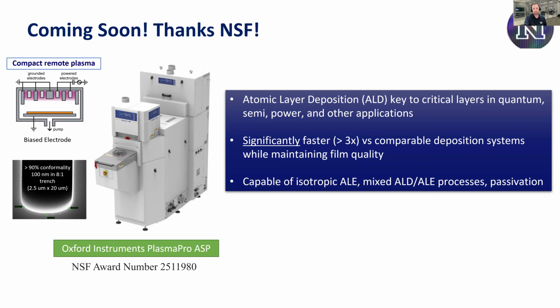We want to be able to control that barrier, but it's really tough because with ALD, when you grow things, if you want like a 2 nanometer thin film, due to nucleation delays and such, you'll oftentimes get this kind of island-like growth. So if you can overgrow this and then etch back, and they've shown this in Steve George's group as well as Erwin Kessel's group at TU Eindhoven, you can get really nice, smooth, ultra-thin, pinhole-free films. So this is an area that we think is really, really exciting. And so we've got some proposals that hopefully I'll get submitted in the next 7 days to look at this that we're super excited about. And that's one of the things we want to do in our tool.